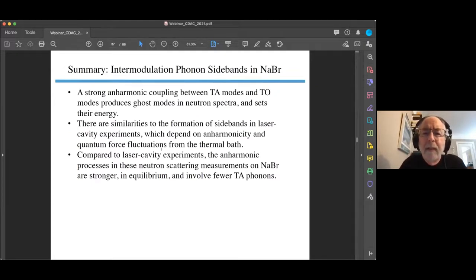Okay, this is a new anharmonic effect, intermodulation phonon sidebands, we call it. It has similarities to the laser cavity experiments, but these are natural processes occurring in thermodynamic equilibrium, and there are fewer phonons involved. In principle, like the laser cavity experiments, when we have one of these ghost modes, it's actually an entangled state for the transverse optical and transverse acoustic modes. I don't know if we can use that for anything because they don't live very long, but nevertheless, it's interesting to see the comparison with all the work that's being done on quantum information.